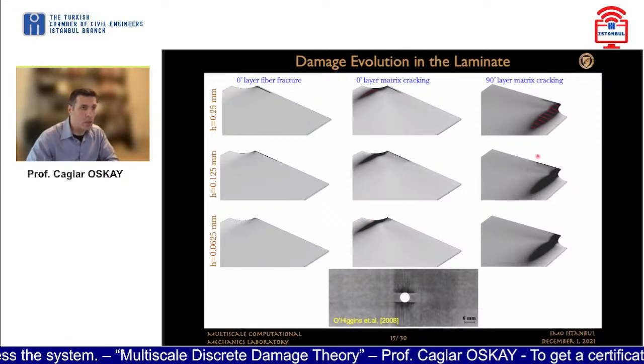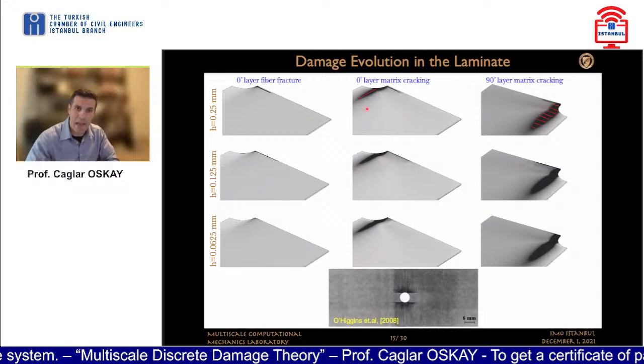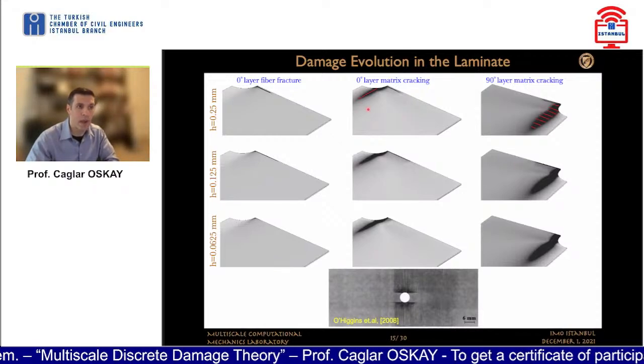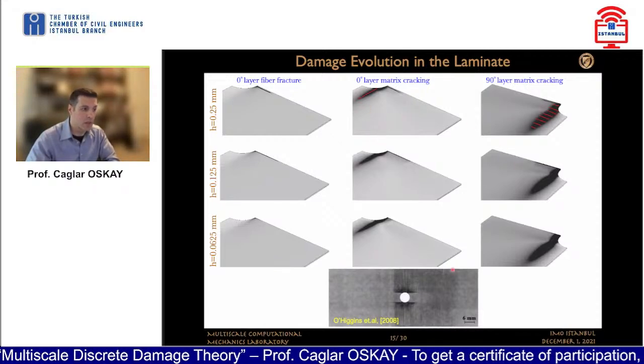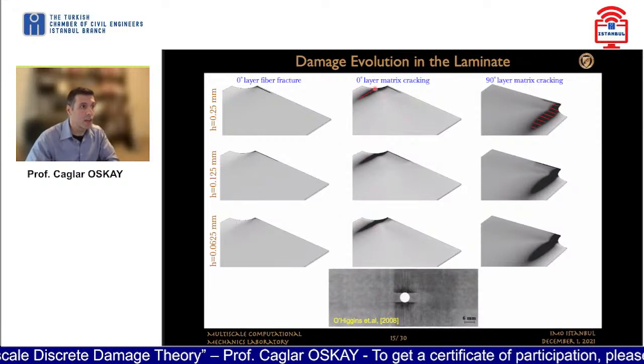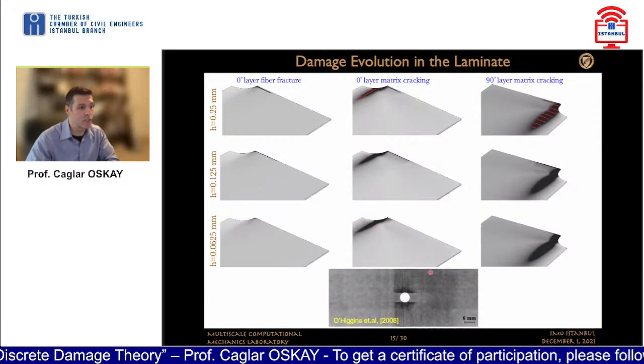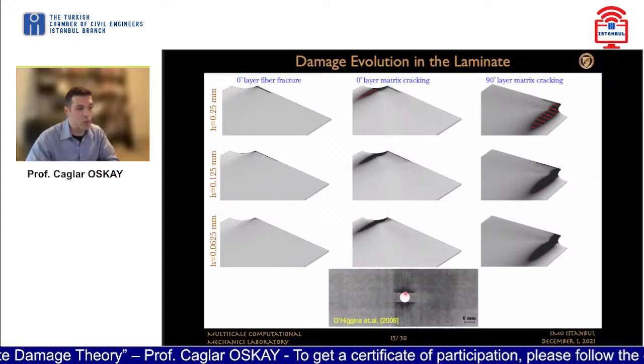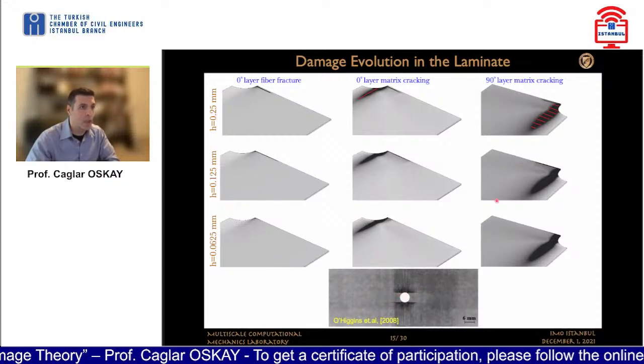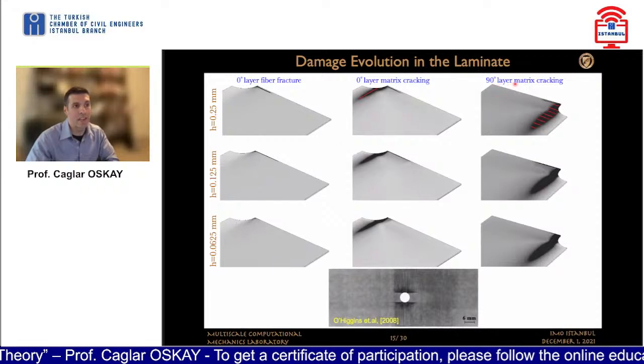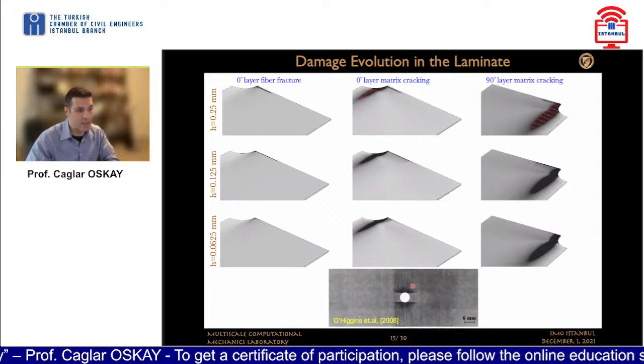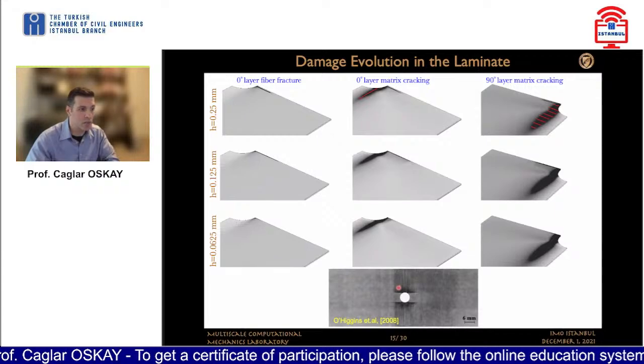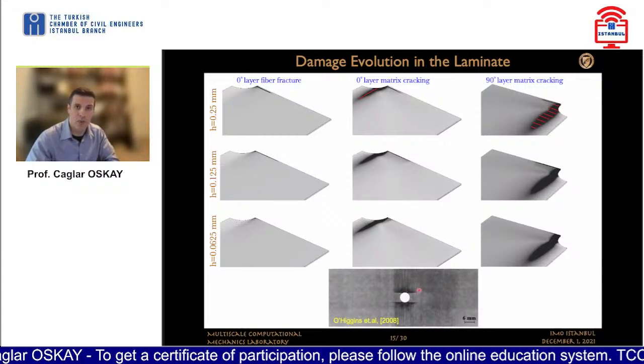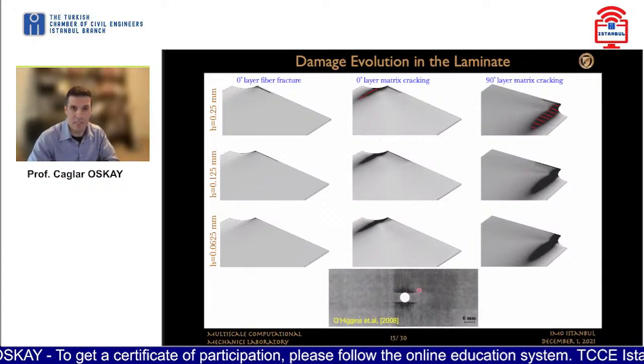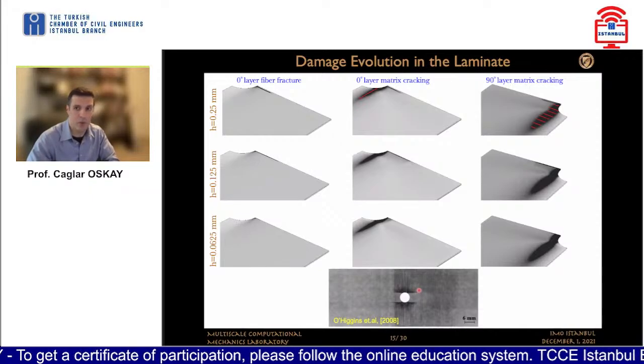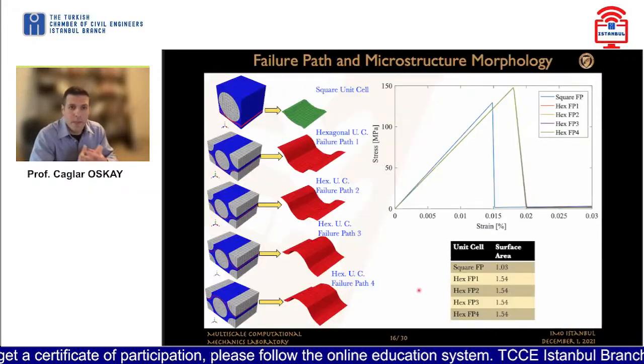And the overall failure cracking patterns also align pretty well with the experimental observations. Here, for example, the 0-layer matrix cracking refers to this horizontal crack that we observe, and the 90-degree layer matrix cracks are the diffuse representation of these cracks that you're seeing in this north-south direction in this little experimental figure. What can you do with these types of materials?